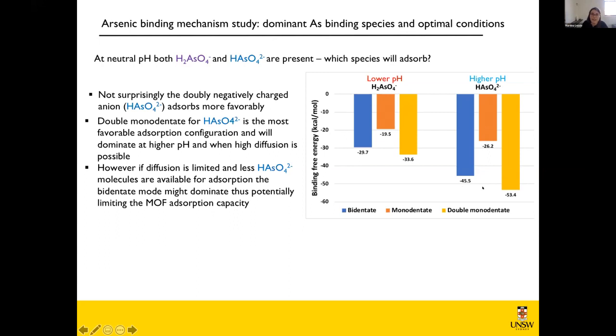And if we are at a high pH with hydrogen arsenate dominating, it's likely that these will end up in a bidentate mode, because the bidentate is more stable than the monodentate by 20 kcal per mole. So it might actually be safer to be at a lower pH, where there is a smaller difference between the bidentate and the monodentate. So we might have a chance at getting a monodentate absorption that would leave space for a second arsenic to absorb and maximize absorption performance.